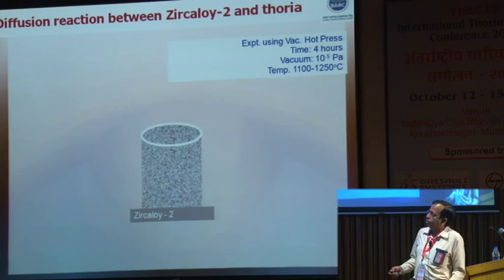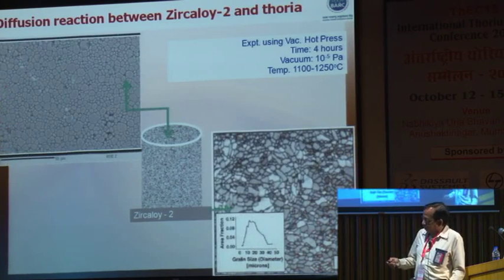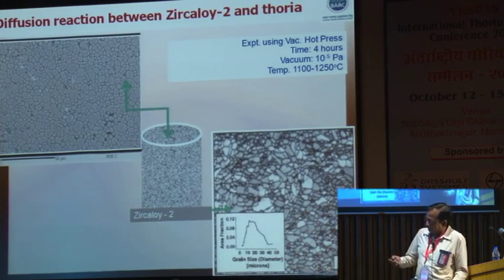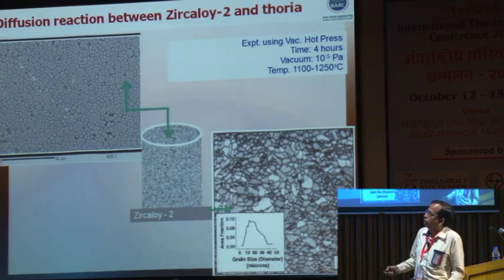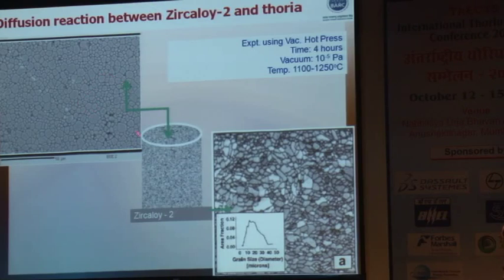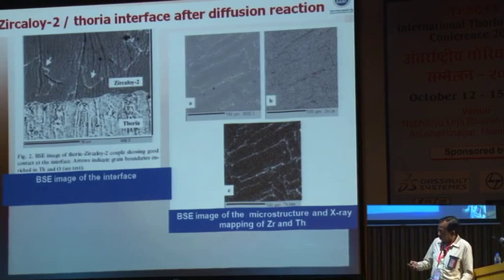So we also have some experience of the interaction of thorium with the clad. For instance, this is thoria and zircaloy as clad here. This is the zircaloy microstructure, and this is the thoria microstructure. And we made a couple of these two to see how these two interact, and the results from that couple are shown here.